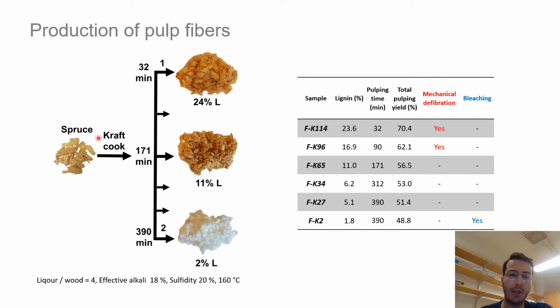I took spruce wood chips and did standard Kraft cooking. You can see the conditions here, but I took different samples at different cooking times, and then I got pulp fibers with different amounts of lignin. To prepare pulp fibers with high amount of lignin and short cooking time, I also had to do mechanical defibration to separate fibers from the wood tissue after cooking. And to get pulp fibers with very low amount of lignin, I also did delignification bleaching on the sample. You can see that the pulp fibers are called FK114 up to FK2. This is the kappa number, the number which comes after K, and this is a measure of lignin content. You can see the legend on lignin content here if you want to have a clearer look.